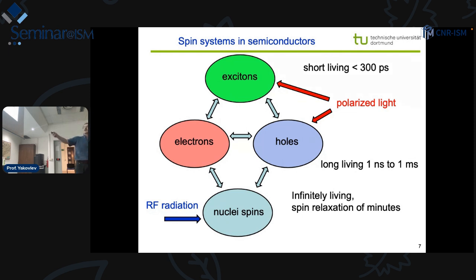In perovskites, we will show that at low temperatures, these carriers can have lifetimes up to 1 millisecond. Excitons, electrons and holes we can generate by circularly polarized light, so their spins will be oriented by light. And we can also read out their polarization by emission, so we can understand whether they are still polarized or not.